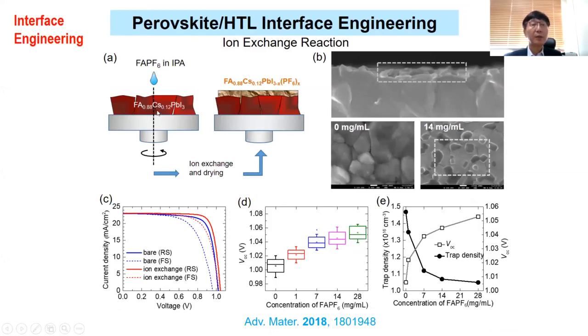After you deposit and anneal the perovskite film, the surface is exposed to the air or environment. Therefore, there is some degradation on the surface of the perovskite, so you need some interface engineering on the perovskite surface. The interlayer can passivate between the perovskite and HTL. By doing this, you can increase the open circuit voltage significantly and at the same time decrease the trap density. Therefore, you have increased open circuit voltage and fill factor.